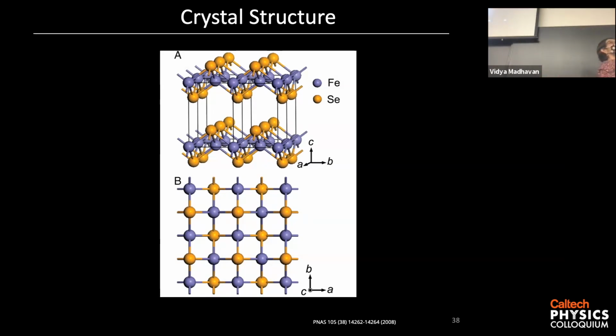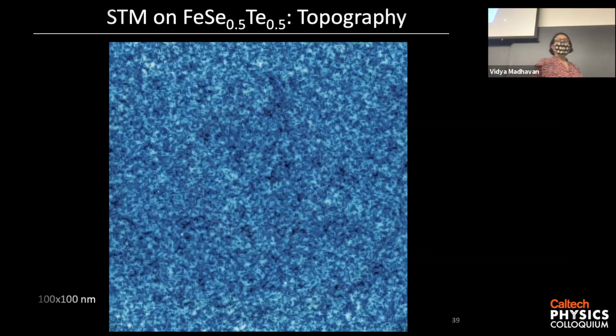So you can imagine that the crystal chooses this configuration, but the same crystal might have other regions where this thing is flipped. So you can have a lot of boundaries in this material between one configuration and another. Okay, so you can just take this thing and flip it, and this thing will be at this position, which is half a unit cell shifted. So when we look at the surface with an STM, we only see these top tellurium atoms, which form this top plaquette. And so this is what an STM image looks like.